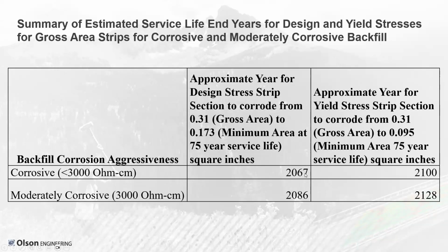But it shows it going to 2067 to 2086, which means that the yield stress strip section where it would really fail would be 2100 to 2128. So the bottom line was there could be zones of localized severe corrosion based on the backfill soils, but most of it was in corrosive to moderately corrosive, less than 3000 ohm centimeters.